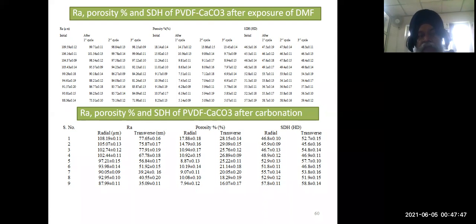Then we reverse this, right? This is the exposure of the DMF. Then in the second case, we give an exposure of the carbonic acid, right? So you see, we started with 109, and with the exposure on the radial side we get 108 again. Similarly, the porosity, you can see it was 18, so we get a porosity of 17.88.